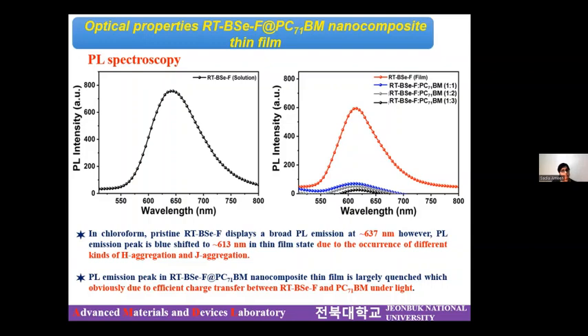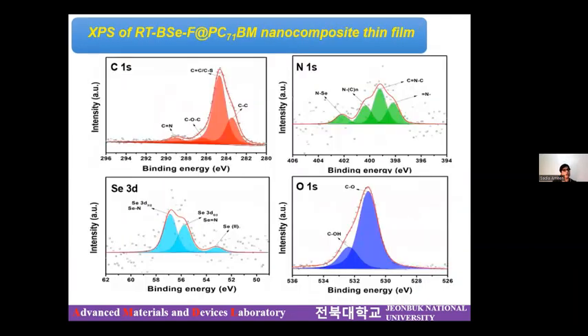But the interesting thing that we obtained in the case of the nanocomposite material is that when these nanocomposite materials are prepared, the PL intensity has been quenched, meaning the intensity of the peaks of nanocomposite materials is reduced, which itself shows the efficient charge transfer between the molecule as well as the PCBM moiety. And furthermore, we have done the XPS spectroscopy just to make sure of the chemical interactions in the synthesized nanocomposite material.